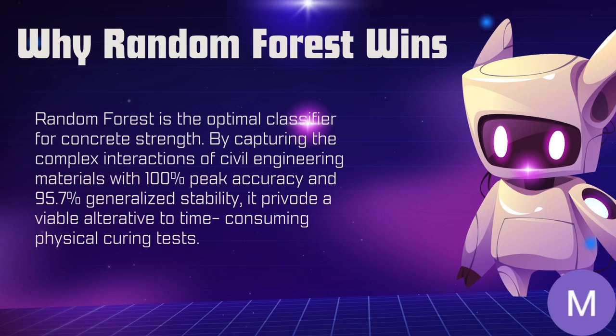The main reason random forest is our preferred model is because it can capture complex relationships between concrete materials and their properties. It achieved the highest prediction accuracy of 100% and maintained a cross-validation accuracy of around 95.7%, showing that the model is both accurate and reliable. This demonstrates that machine learning can support engineers by providing fast and dependable predictions, reducing the need for repeated physical testing.